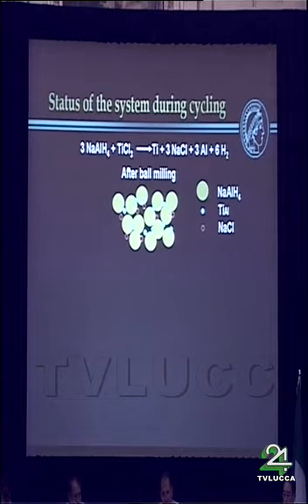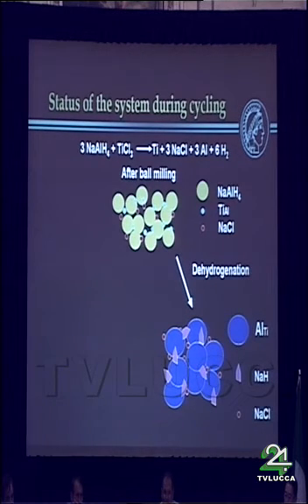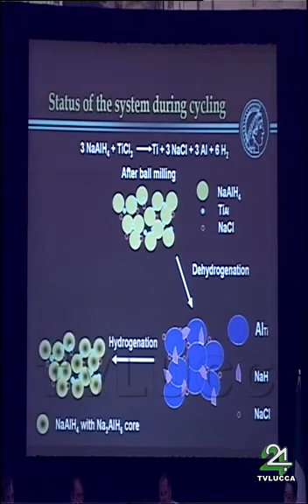After ball milling, we have sodium alanate, titanium at a high concentration in aluminum, and sodium chloride. When we decompose, we have titanium in the aluminum at a very low concentration, because now the sodium alanate has decomposed to the aluminum, sodium hydride, and the remainder of the sodium chloride from the doping. And then it cycles back and forth between sodium alanate and the dehydrogenated state, and the titanium basically just changes concentration in an aluminum matrix.